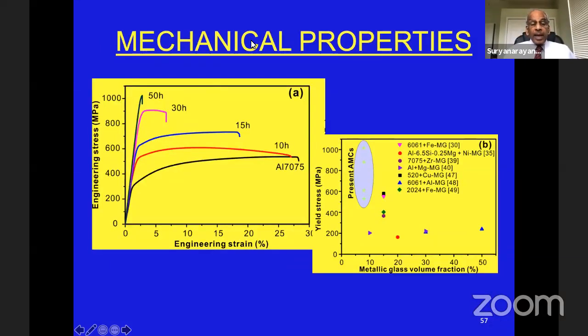If you now look at the mechanical properties, you can see you can reach almost like a gigapascal strength, which is very high for an aluminum alloy. And of course, the amount of time for which you mill is important. If it's a very low timing, it is not very high, but by 50 hours, because the grain size is going to be decreasing, you'll be able to get very high tensile strength.